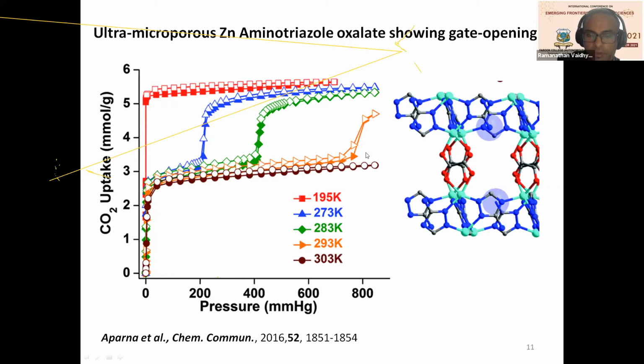That same phenomenon starts to shift to a lower pressure as you decrease the temperature, which is expected. The fundamental Charles' law would tell you why the gating pressure shifts to a lower pressure as you decrease the temperature. And you see that, but at 195 Kelvin, the structure does not show any such flexibility, but is very open and a lot of CO2 is able to get in.